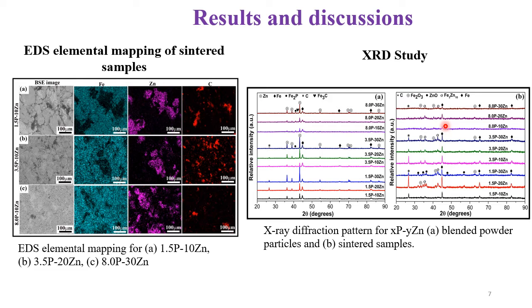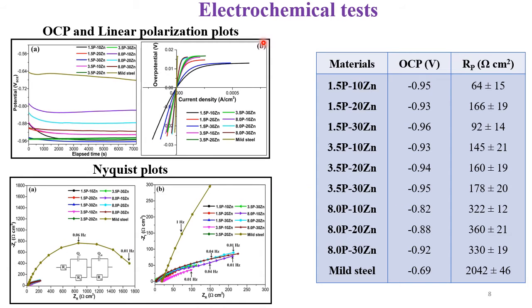And the XRD study reveals formation of Fe3Zn10 intermetallic in the case of all the hybrid samples. Along with that, various oxide phases of iron and zinc have been formed on the surface due to sintering in the open atmosphere. Coming to the electrochemical behavior, as can be seen, the OCP of all the hybrid samples shows more active behavior as compared to the mild steel.